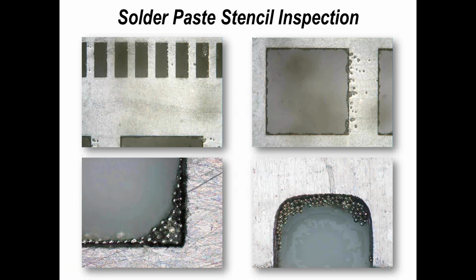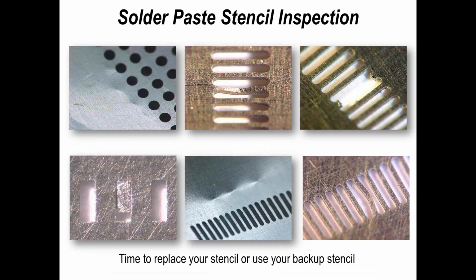So whenever you're looking at visiting a vendor or looking at your own manufacturing facility, make sure you can clean a stencil effectively. And possibly there's a benefit in having some form of semi-automatic cleaning process as part of your process to guarantee that when you do clean a stencil or touch up a stencil, many of us do on a line, that it's effective in the way in which it's removing solder paste from an aperture. Ultrasonic energy has been used as an assistance for a cleaning process over the last few years in quite a few manufacturing facilities in Asia.